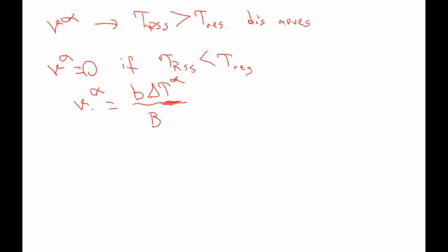And this drag coefficient is a function of sometimes temperature, sometimes if you have additional solutes in your material, C, and we have B0 plus tau B1. And if you go ahead and check some papers, you will see that it is on the order of 10 to the minus 4.